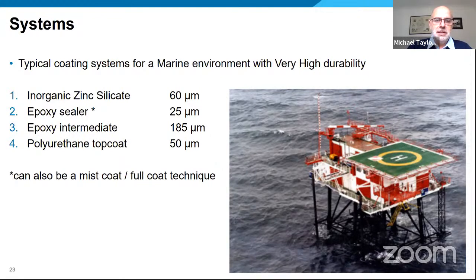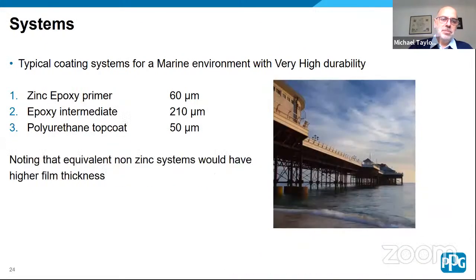You could use it as one coat of sealer, or you could use it as a mist coat using the epoxy intermediate at 210 microns, as a mist coat, full coat technique. With the zinc epoxy primer, you don't need a sealer coat. You can just apply the intermediate coat directly onto the zinc epoxy primer. And as I mentioned before, noting that equivalent non-zinc systems would be approximately 40 microns higher to get the same durability.